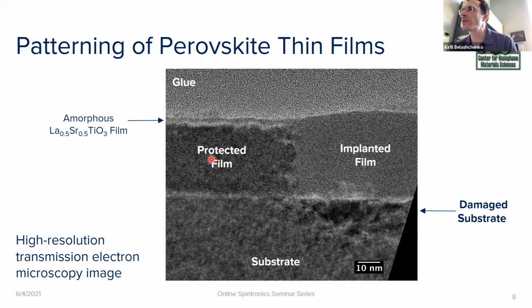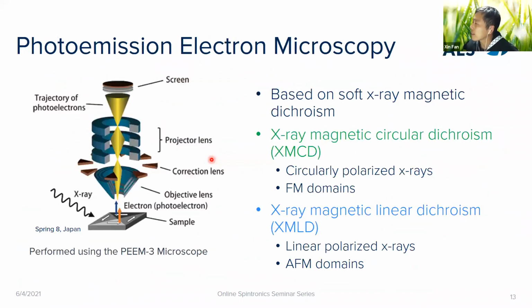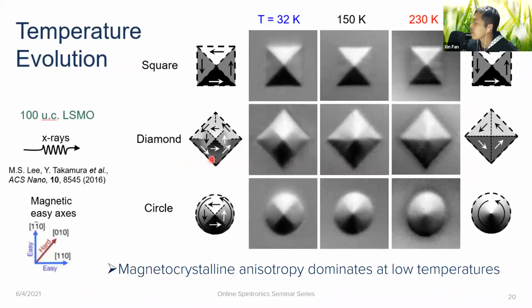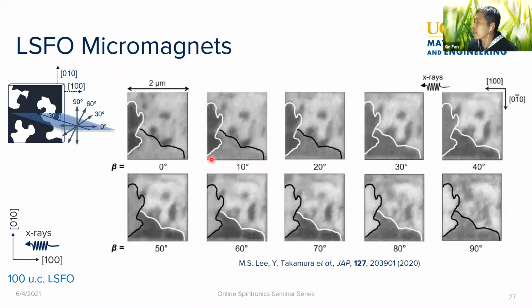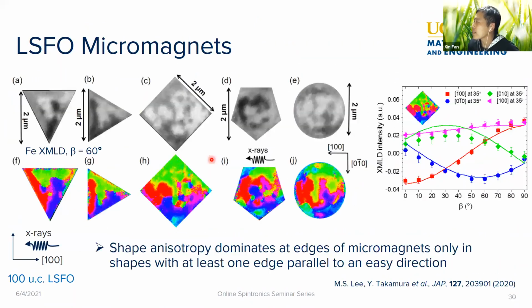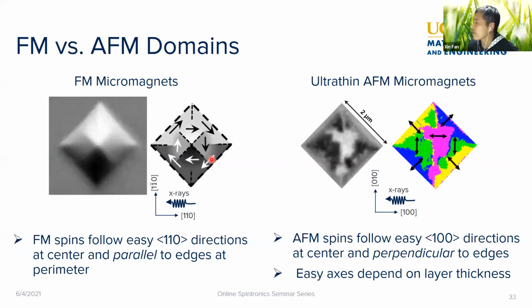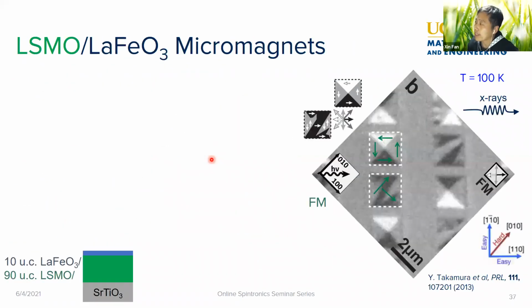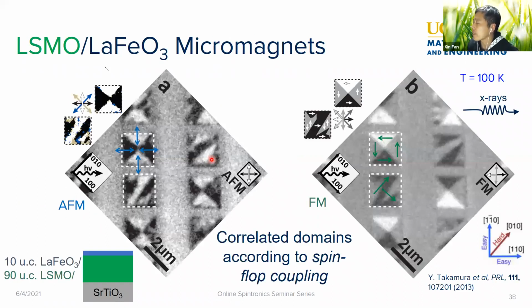Shen, would you like to ask a question? Sent one through chat. Yeah, I can ask just in case my Zoom freezes out again. Sorry, it's been very unstable at this moment. So you showed that with the Zorro patterns and the Landau pattern, it seems that in the exchange coupled films, the ferromagnetic domains and antiferromagnetic domains are strongly coupled. So does it mean that if I can use an external magnetic field to rotate the ferromagnetic domain, I can actually change the antiferromagnetic domain?